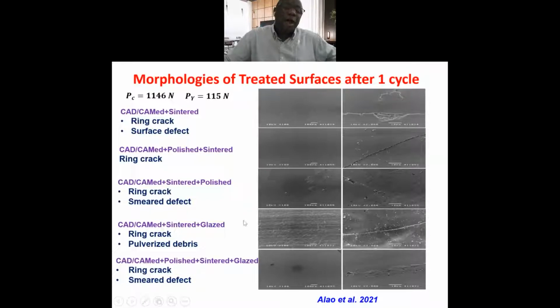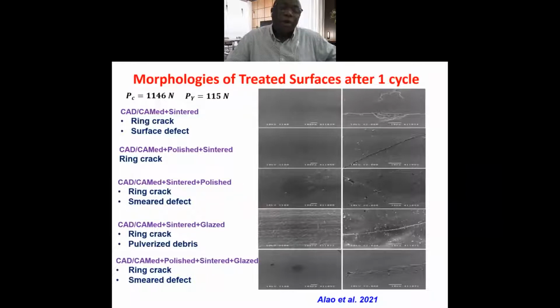So now I use the formula shown in the previous slide to calculate the critical load for the cone cracking, and based on our experiment and material properties for the cone crack, the critical load is supposed to be 1,146, which was greater than the maximum load, that is 800. So it is possible that cone cracking did not occur at one cycle. However, the critical load for the quasi-plastic yield was 115 Newton, which was lower than 800. So it means quasi-plastic yield occurs.